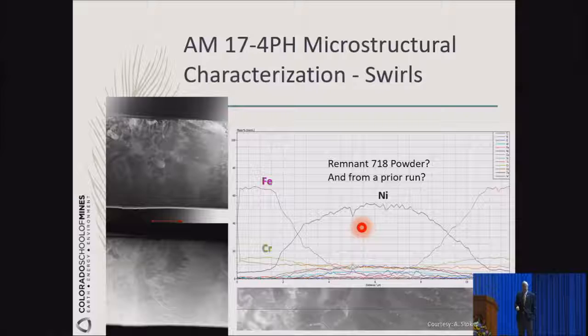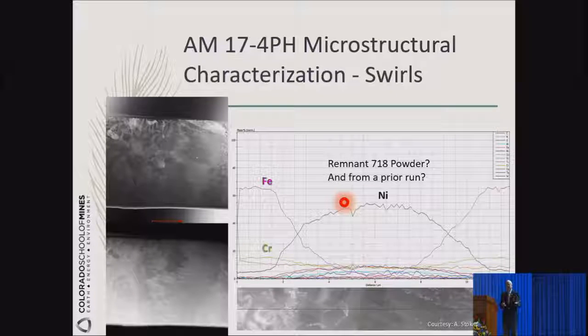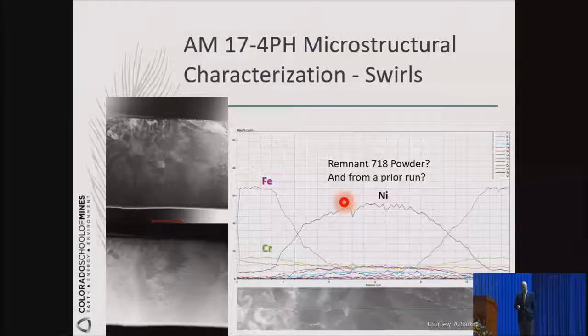Then a little bit of the TEM work here and also the STEM work. You notice the nickel composition goes up, and it says 718. So now that begins to bring in another question. Did the manufacturer screw up in the sense that they mixed powder? Was it a totally, fully clean system before they started building the 17-4? So those are the questions that we have. If it were only by the welding, by the deposition itself, and it partitioned itself, distributes itself as the 718, we have a major problem to deal with to get it back to a more uniform composition. If it were more of an operation failure, then it's just basically cleaning the system and all that. But that remains a problem to be resolved in the industry.